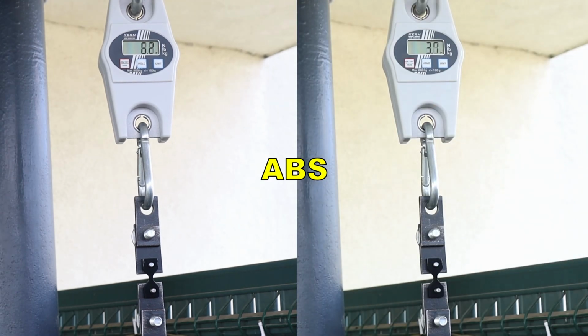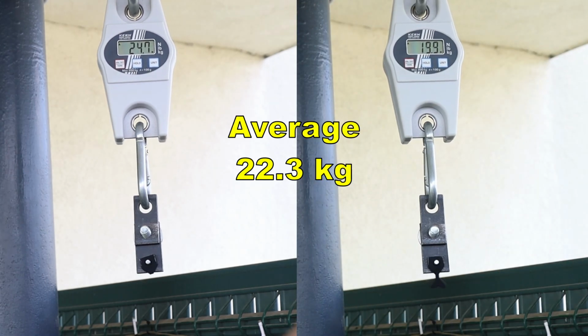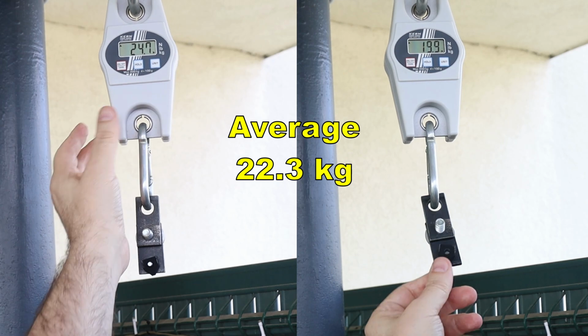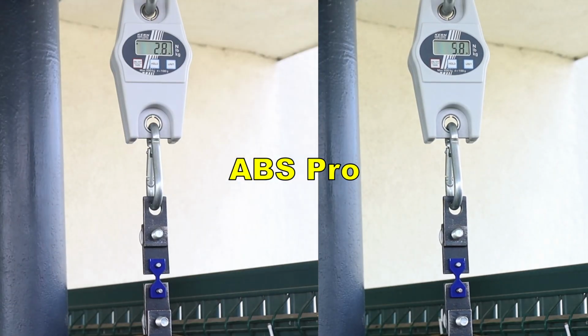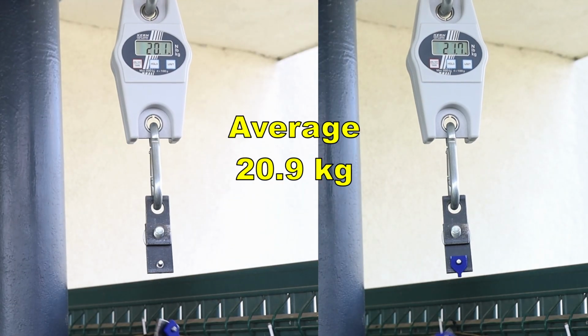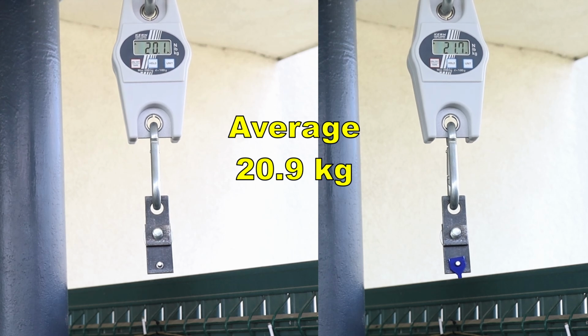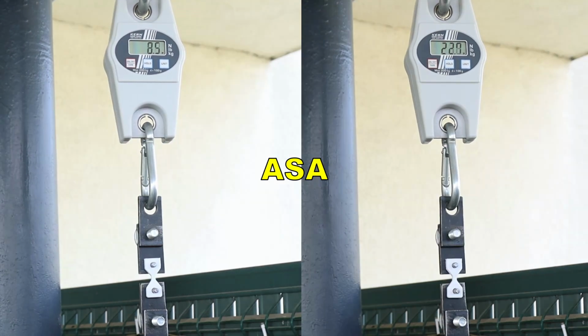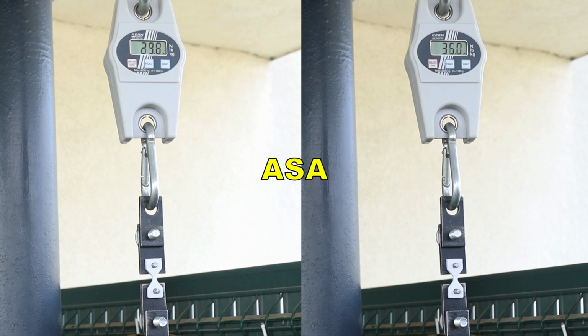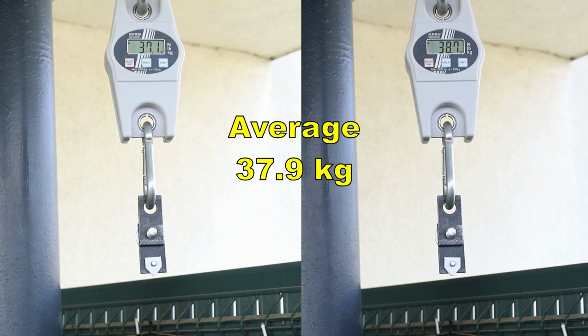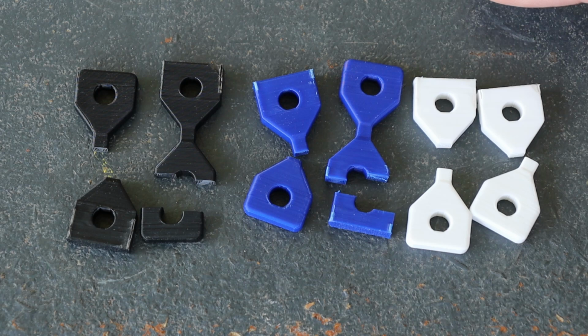Again, starting with ABS. Around 20 kilograms, this is on the edge of acceptable. ABS Pro, similar. ASA. Stronger, much stronger, 37.9 kilograms.